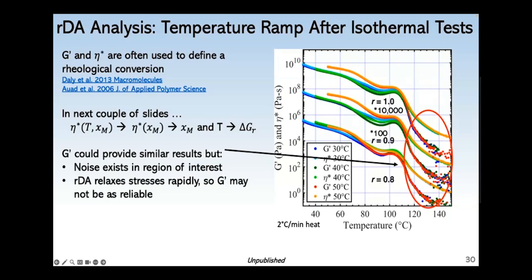Both of those variables, G prime and eta star, have been used in other research to define a rheological conversion, but these are usually not tied to the absolute conversion of functional groups. One of the other difficulties in performing rheokinetics analysis is that both of these variables have a temperature and a conversion dependence. I chose to work with complex viscosity, and in the next few slides, my goal was to account for the temperature dependence on the complex viscosity, therefore making it only a function of the conversion, and then calculate the conversion and use the high temperatures to perform an equilibrium analysis, all in the end to calculate the reaction thermodynamics.